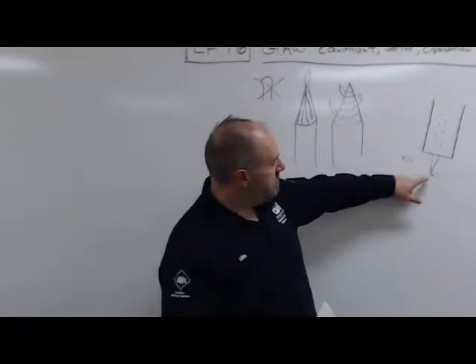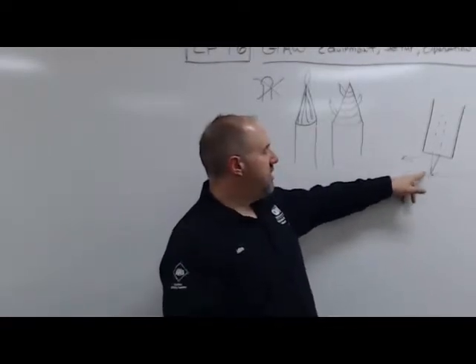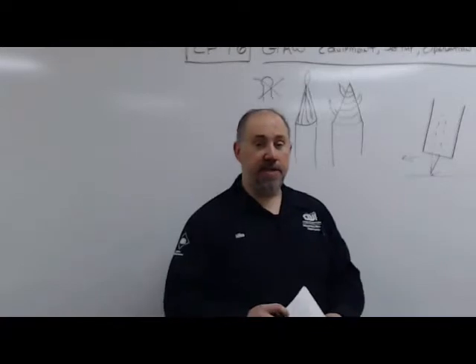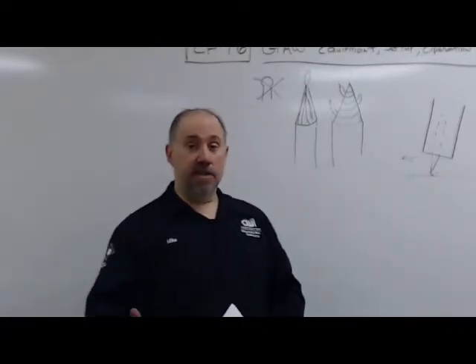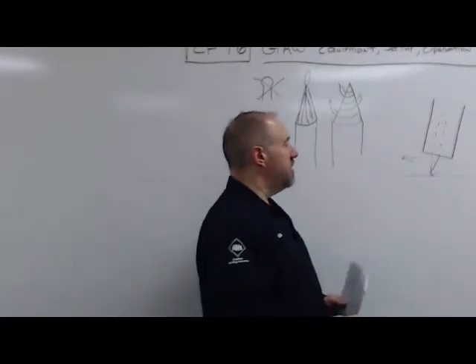For me, on 10 gauge, which is what we're going to start off with, that gap's going to be 3/32nds of an inch, which is about my filler metal diameter. It's also my tungsten diameter if you need a visual reference. I'm going to be really close.